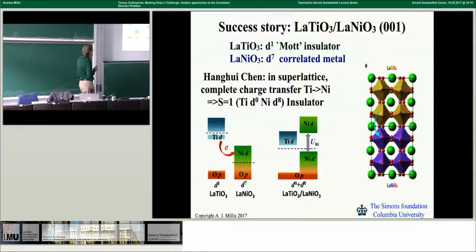So let's take two materials, lanthanum titanate, LaTiO3, and lanthanum nickelate, LaNiO3. In bulk, lanthanum titanate is a so-called Mott insulator. That means that if I use the conventional reasoning of electronic structure theory, essentially because it has one electron in the titanium D shell per unit cell, it should be a metal. It has a partially filled band. Right? In fact, it's an insulator. And the reason it's an insulator is electron correlations. Essentially, because of electron-electron interactions, electronic motion is jammed or blocked, and it can't conduct electricity. Right? Lanthanum nickelate, LaNiO3, is both experimentally and in conventional electronic structure theory simply a metal, right? With some modest enhancement of properties because of electron-electron interactions.